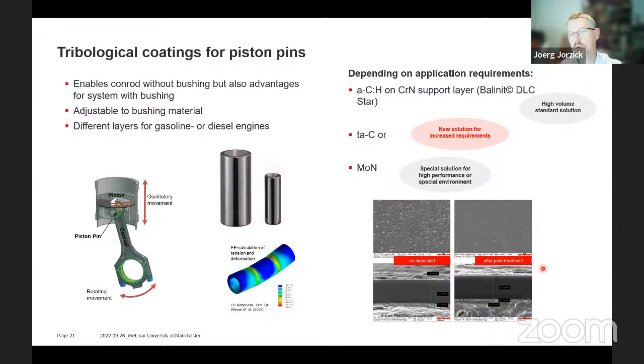So you can go higher in temperature compared to the 300 degree, and this coating still survives it. And there's another case where this molybdenum nitride can be used very well, and that is if some of the DLC coatings can interact with some of the additives in the lubricant. Here I will show you an example later of how the additives can interact with the PVD coating. And for this case also, molybdenum nitride can be a suitable solution, but I will show you more details about that a little later.